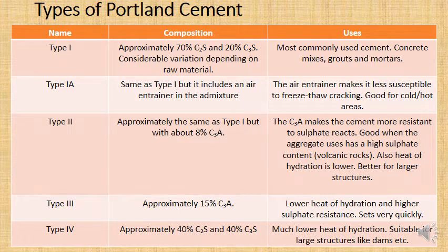Now, that will make the concrete weaker, but it will make it less susceptible to freeze-thaw cracking. And I can try to show this to you on the whiteboard when we have our tutorial, if you like. But basically, there are little air bubbles inside the concrete, which gives water that is sitting on the surface room to expand and then shrink as it freezes and melts.